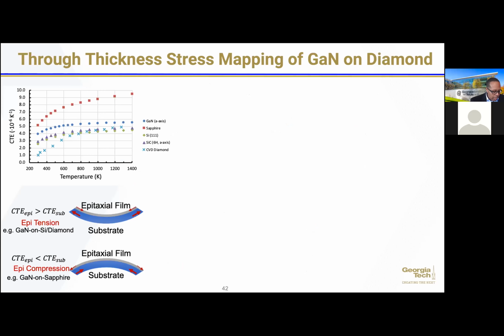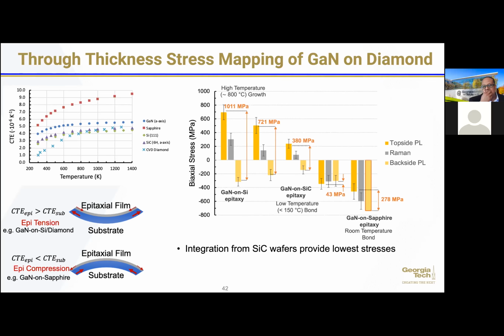So what we know, and again, using this technique, we know that if I have a film where my epitaxial layer has a CTE higher than the coefficient of thermal expansion of the substrate, my film is going to be in tension. And so if the CTE of the epi layer is higher than the substrate, if I grow GaN on a material like silicon here, I know I'm going to start out with a tensile material. If I grow GaN on sapphire and I try to transfer it and bond it, I'm going to start out with a compressive material. And so that's what you see here. So when we start out, we have GaN on silicon epitaxy. I do the transfer bond, even though I'm doing the transfer bonding at low temperatures. What we see are these very large stresses that can exist in the gallium nitride. Or excuse me, I'm sorry, this is the growth. I'm going to get to the transfer bonding next.